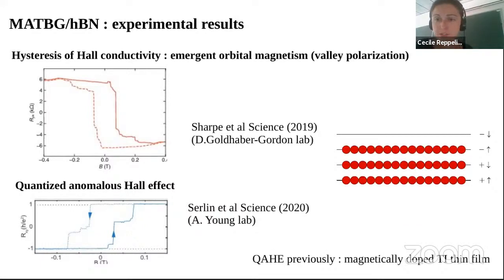Yeah, it's probably important to specify the fact that quantized anomalous Hall effect had been observed previously, but in a very different setting. This is an observation that dates back to around 2013 or so. The material was very different. What they did is they took some thin films of topological insulators.